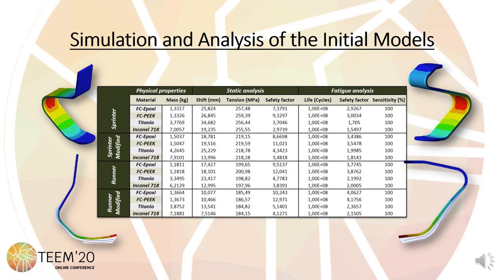Titanium and Inconel exceed the established mass limit by 180% for titanium and 350% for Inconel. Therefore, it should be noted that carbon fiber epoxy and carbon fiber PEEK composites meet all the design specifications established for static and fatigue simulation.